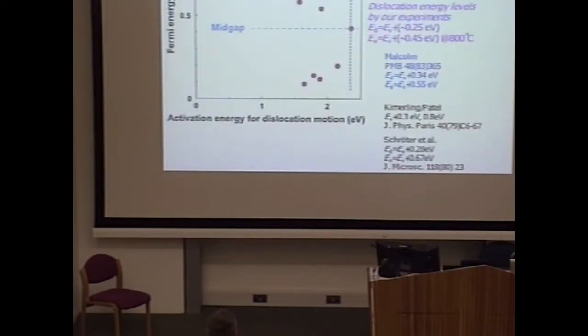So this result shows some kind of comparison between experimental estimations and theoretical estimations. Malcolm reported this result. So the dislocation has a donor level and also acceptor levels from the valence band edge, around 0.34 and also 0.55. Because our result is only from experiments at elevated temperature, some magnitudes are rather different. But maybe they can be corrected by using the temperature dependence of Fermi levels and also band gap.